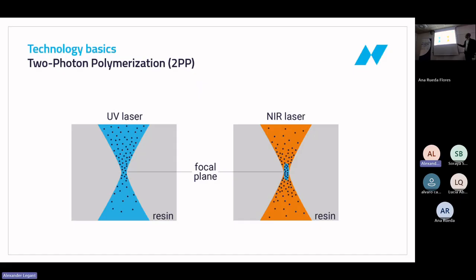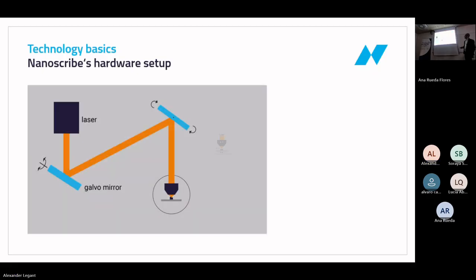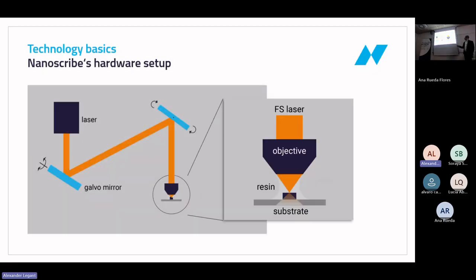But here on the right side, again, polymerization takes place only at the focal plane at the laser focus. Now what we do is provide two different types of autofocus to find a starting point in Z direction. One uses the reflection from the interface between resin and substrate. The other type of autofocus uses the fluorescence inside the material. And like this, we define the starting point in Z direction.